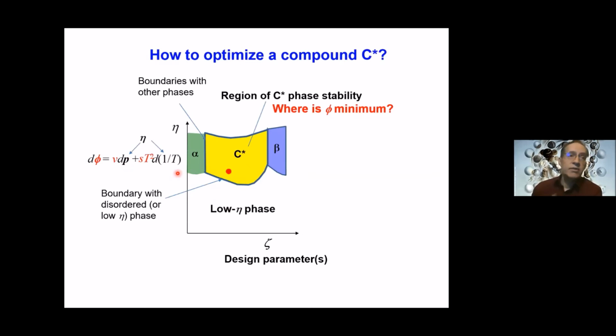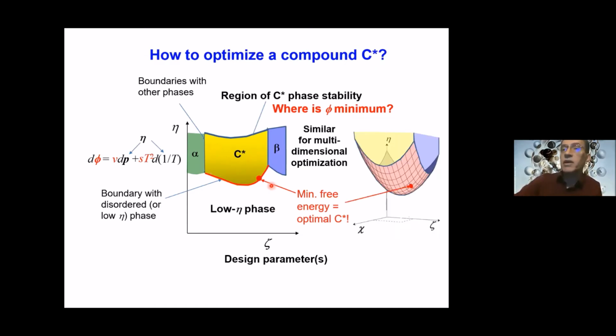Now, if you look at this equation, which is just the fundamental thermodynamic equation for the Gibbs free energy, you will see that the coefficients, volume and entropy T squared, are always positive. That tells you that the free energy can only increase as you increase along any of these two axes eta. So you don't need to be looking for the minimum free energy everywhere, but only along this boundary, right? This also makes practical sense, because in practice, if you want to access the C star phase, it will be from the isotropic state, through some kind of crystallization. So we just need to map the free energy along that boundary and find the place where it's minimum. Of course, the same idea applies if I had multiple design parameters: I just need to find that point on that phase boundary, as shown over here.